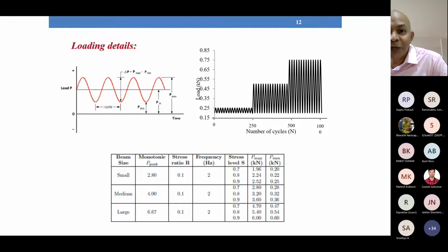These are the loading details. This is the constant amplitude loading, and then we have the variable amplitude loading. In the constant amplitude loading, what I'll be presenting is the test performed with a frequency of 2 Hertz. We have carried out tests with different frequencies too. The stress ratio, that is the ratio of Pmin to Pmax, is 0.1. In the fatigue test, the minimum load is kept at a small value, about 0.2 kilonewton, to avoid separation of the loading device from the specimen, so that contact is always maintained.